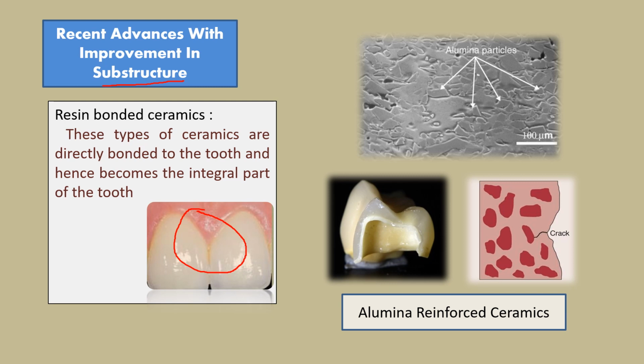And as already discussed, this alumina is a strong crystalline material which doesn't allow the crack to propagate through it. And in this same image, we can see these alumina particles dispersed within the porcelain, and this dispersion resulted in the alumina reinforced ceramics, which was introduced by McLean in 1960. These alumina reinforced ceramics are used for restorations in anterior teeth and cannot be used for restorations in posterior teeth because of strength concerns.